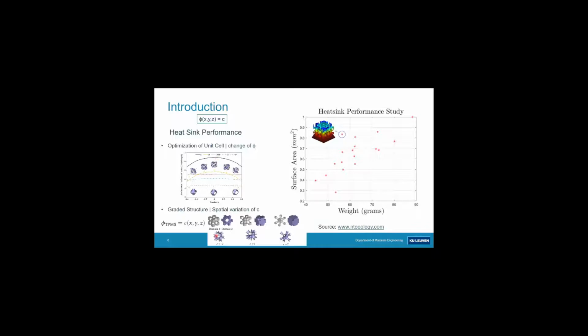Now, when you construct these kinds of surfaces, you create 2 types of domains, and by varying the C parameter in your function, you vary the volume fraction of each phase. This allows you to structurally design, for example, in certain regions of your heat exchanger where there are certain mechanical requirements, and then you can increase the fraction of solid phase to provide more strength. So you can also make graded structures as such. This can all be expressed as a mathematical function or a combination thereof, and you can describe it in an STL file, so you can directly load it in your printer.